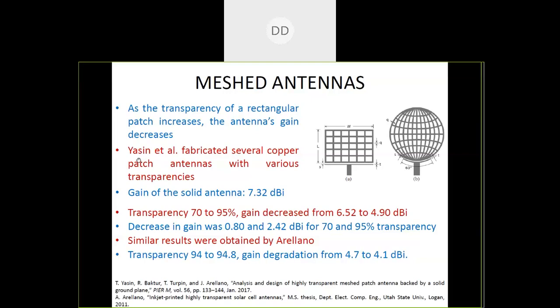A team of scientists led by Yasin fabricated several copper patch antennas with various transparencies and analyzed the gain. In one particular example, they had a solid antenna of 7.32 dBi gain. When they changed the transparency of the antenna from 70 to 95%, the gain decreased from 6.52 to 4.90 dBi. So gain decreases as the transparency of the antenna is increased. Similarly, the decrease in gain was 0.8 and 2.42 dBi for 70 and 95% transparency for this second structure, which we have shown here.